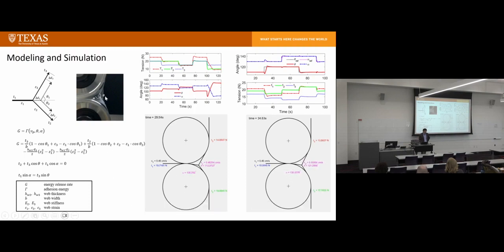You can see this is the incoming web, and then after separation, you have two webs going out. And there's always a peeling angle here. We use theta and alpha to represent these peeling angles. If you change the tension over here, your peeling front is actually moving because of the balance between energy release rate and adhesive energy. Depending on the tension, it's actually very hard to model because this is peeling front geometry.